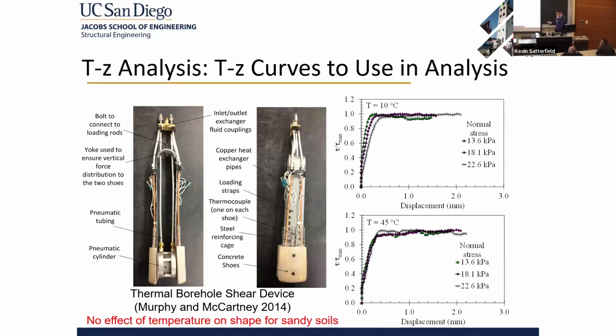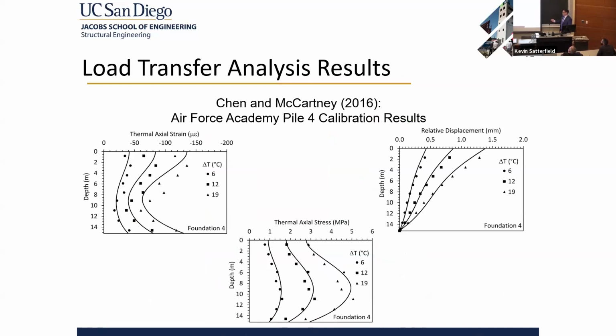We wanted to simulate these then with our load transfer analysis I told you about. So we had a special device that we lowered down in the hole. It's similar to the handy borehole shear test. We expanded this against the side of the pile and pulled up. And we were able to get these t-z curves for different temperatures and normal stresses, and temperature had a negligible effect. And we were able to then match these with our measured values, and we got good results. We did have to calibrate the springs at the head and the toe of the pile. We didn't know those a priori, but from the side shear, we got a good response.